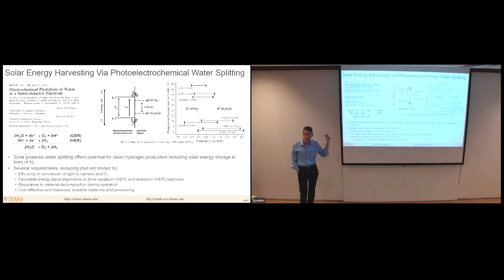So this is something that has actually been known about for a long time. The first paper reporting this is this very famous paper by Fujishima and Honda, showing that this approach can be used to split water molecules into hydrogen and oxygen. And basically, the way it works is that if you have a semiconductor absorber material and you shine light on it, say sunlight, then you create electron and hole pairs. And if the band gap of the semiconductor is sufficiently large, it has to be larger than the difference in the redox potentials for the water splitting reactions. This difference is 1.23 electron volts. So you need slightly larger band gaps. And if they're properly aligned with the redox potentials, then the electrons can participate in the hydrogen evolution reaction, H+ to H2, and the holes can participate in the oxygen evolution reaction, OH- to eventually O2 and H2O.